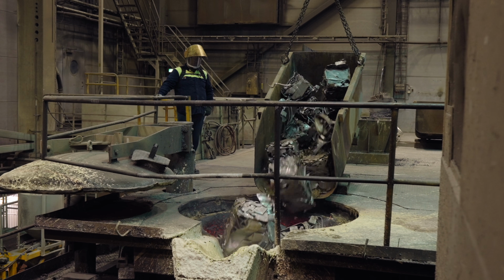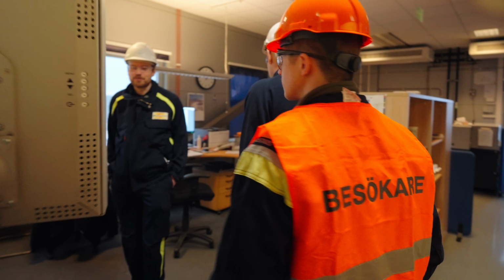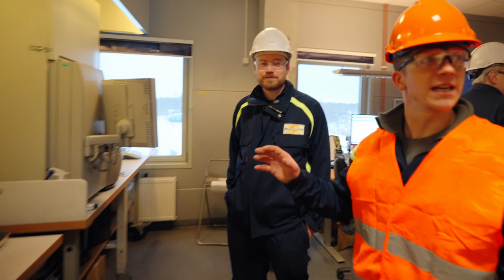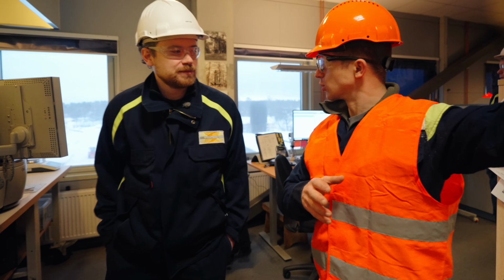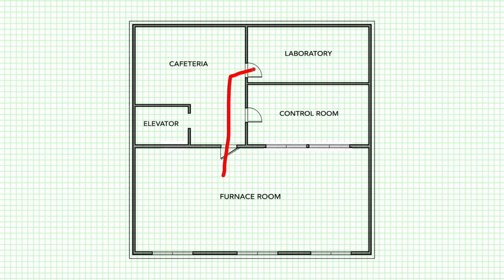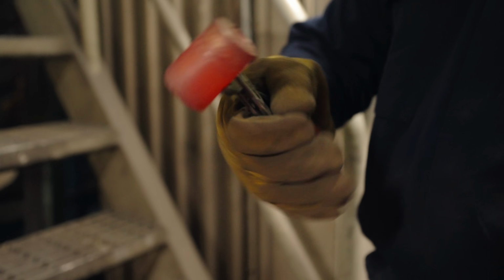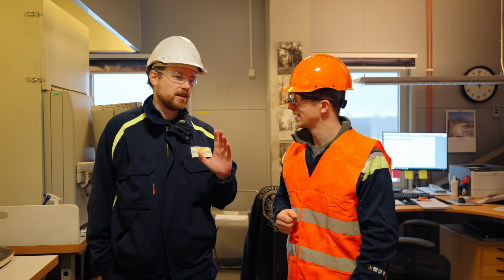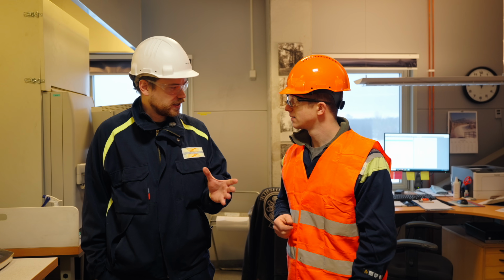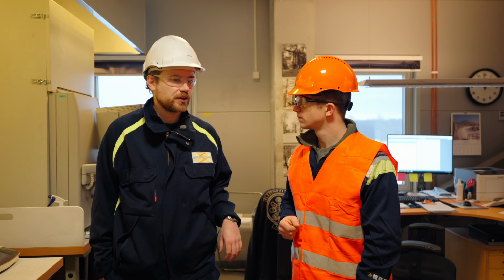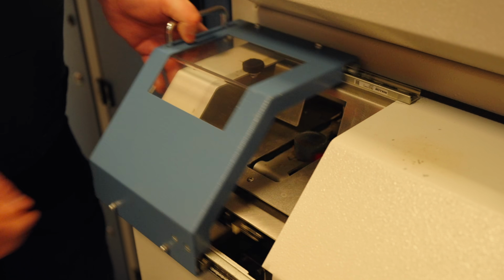That is incredible. All right, so this is the chemistry lab. And this is right next to the control room, the other side of the control room in the Atomization tower here. And so this is, as we described earlier, they take a ladle of the molten steel as the melt is developing. They bring it into here, it cools down and it's tested while that batch is still going. Exactly, so the first step is to cut the small ingot into a sizable piece that you can use for analysis. Then we have several steps of grinding and polishing to get the correct surface finish on the sample.